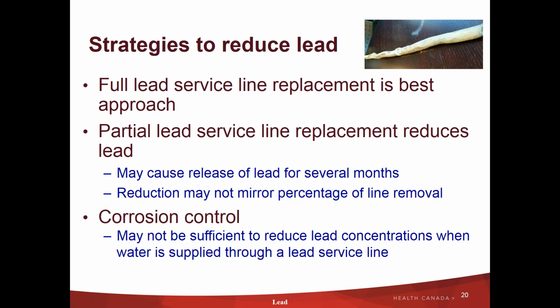So obviously, the big driver is full lead service line replacement as the best approach, recognizing that it's not feasible to do in a very short period of time. This is a long-term plan. Partial lead service line replacement can reduce lead, and we want to make sure we get that message across that it may cause release of lead for several months afterwards, and that reduction might not mirror the percentage of line removal. So if you remove 50% of your lead service line, it does not necessarily mean you will get 50% reduction in the lead concentration you get at the tap. So those key messages need to get across to make sure that we try to promote the full lead service line replacement as best as we can.